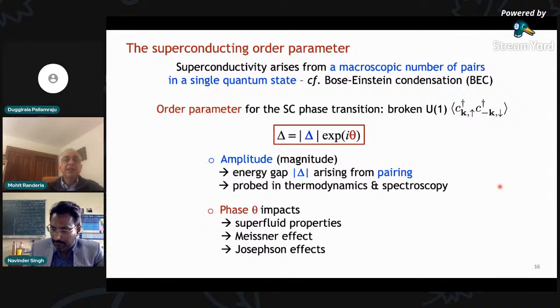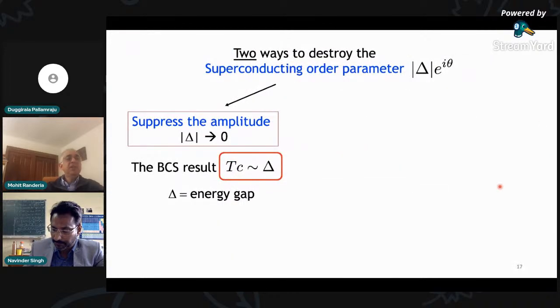So let's ask how this is relevant. Suppose I have an order parameter with an amplitude and a phase, which is locally well defined. Then long-range order could be destroyed in two ways. Either you just suppress the amplitude everywhere and make it go to zero, then of course there's no long-range order. This is the BCS route. The TC just scales like the energy gap, which actually is the amplitude of the order parameter.